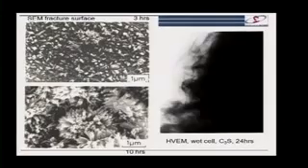And, you know, probably the best approach we can get for not drying a sample is this kind of image, which was taken not in an environmental scanning microscope, but in an environmental transmission microscope, where really we could have almost water liquid present. And here you get this idea that we have these kind of films, and these films are really extending into the pore space in this very filamenty way.